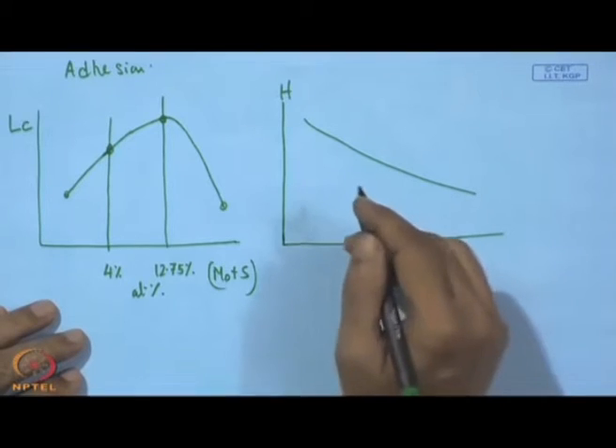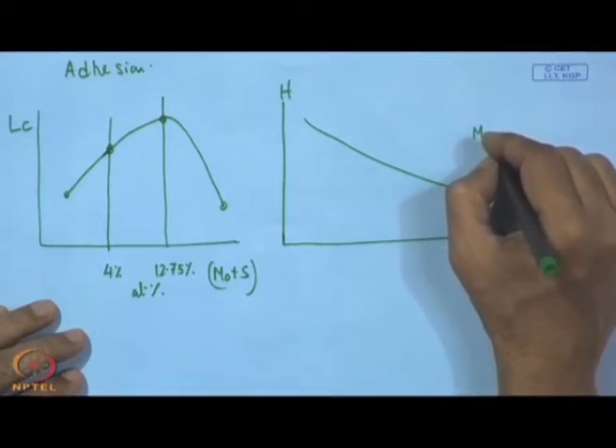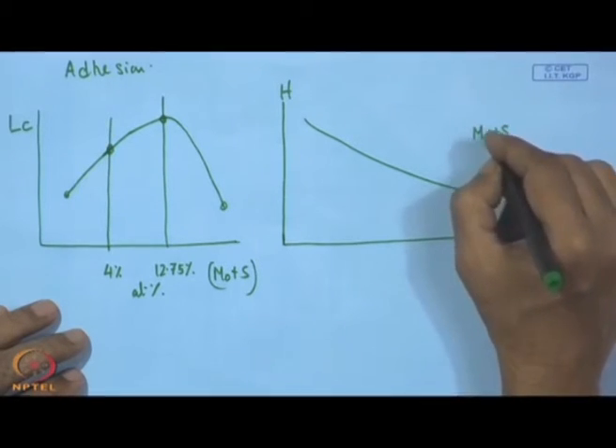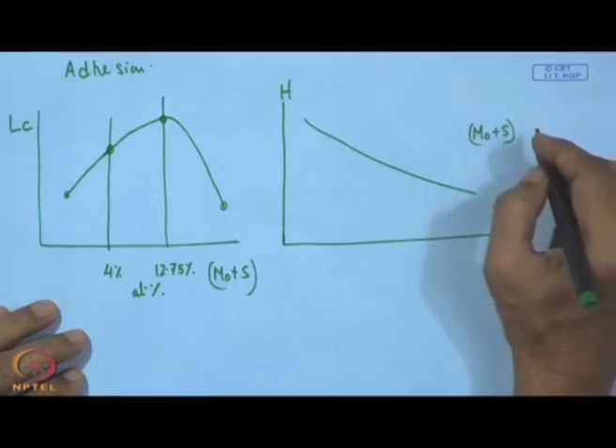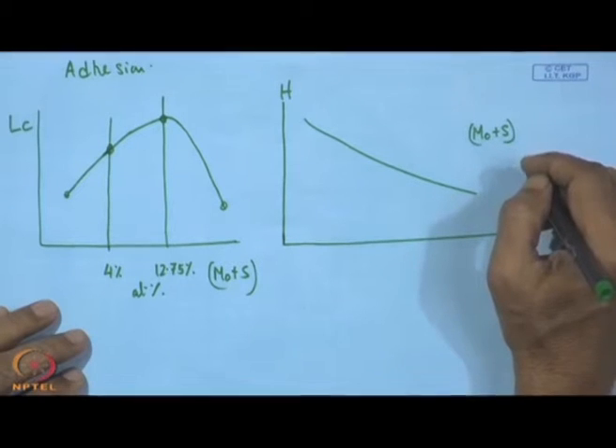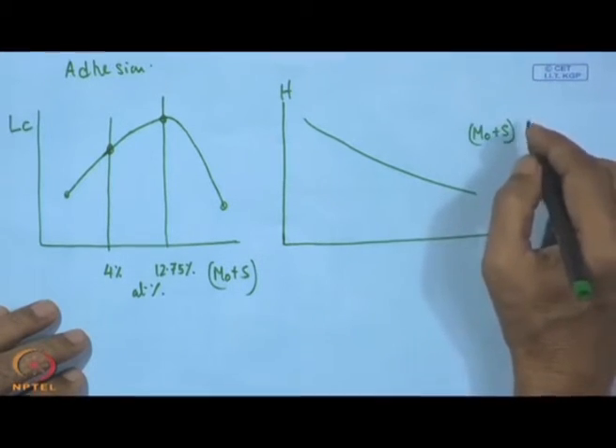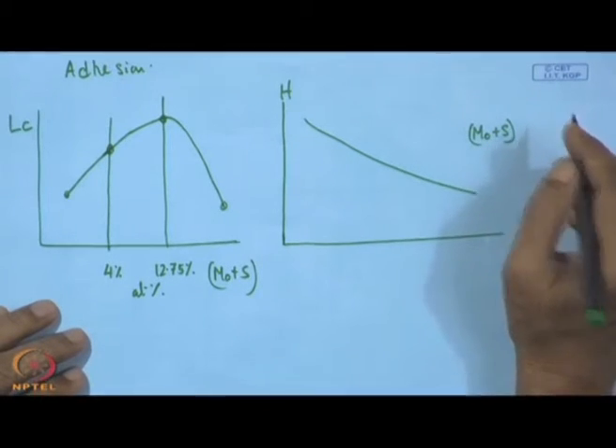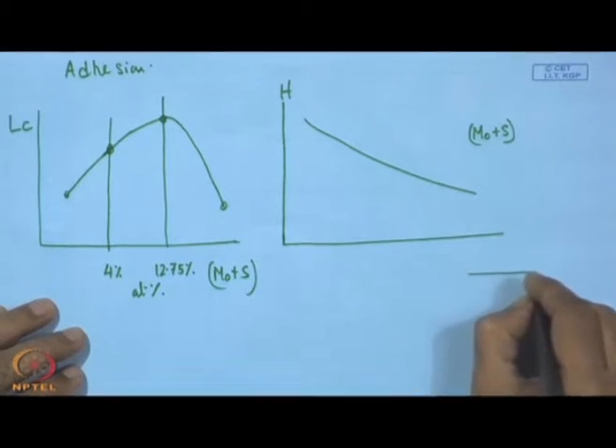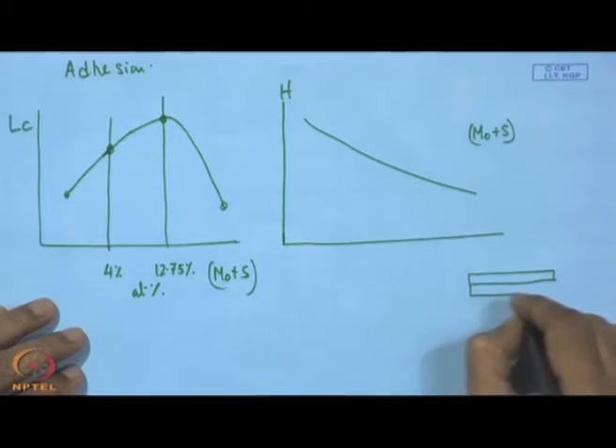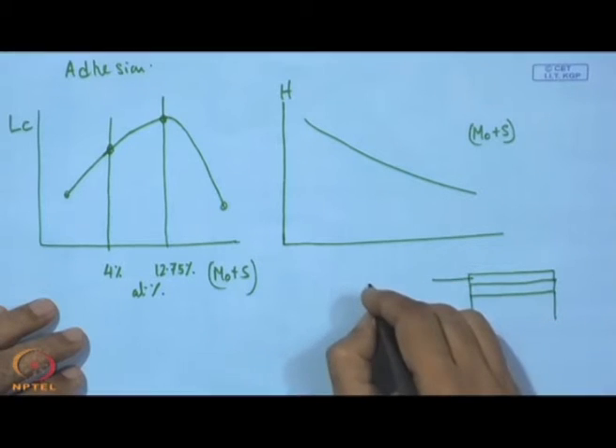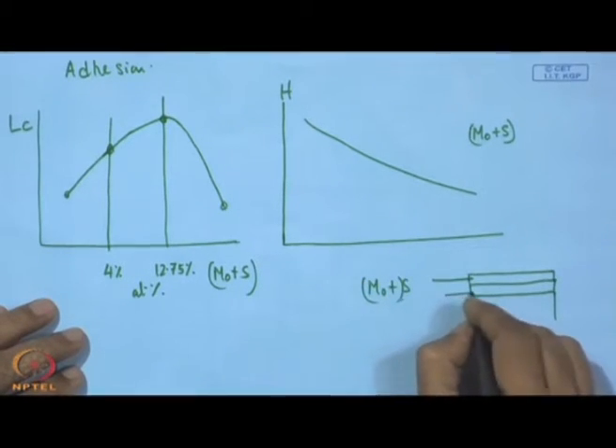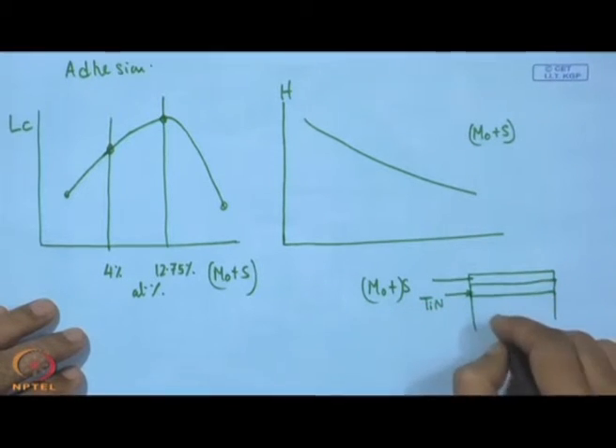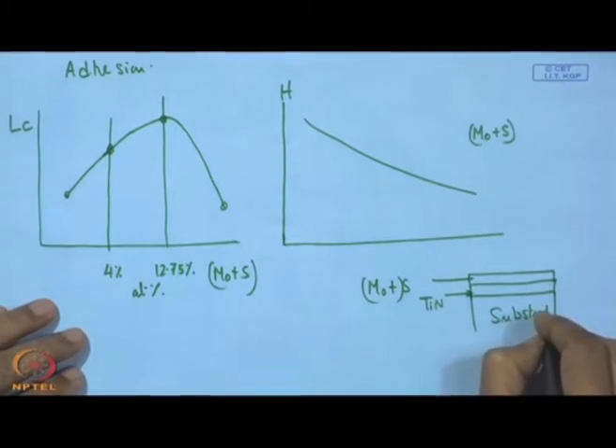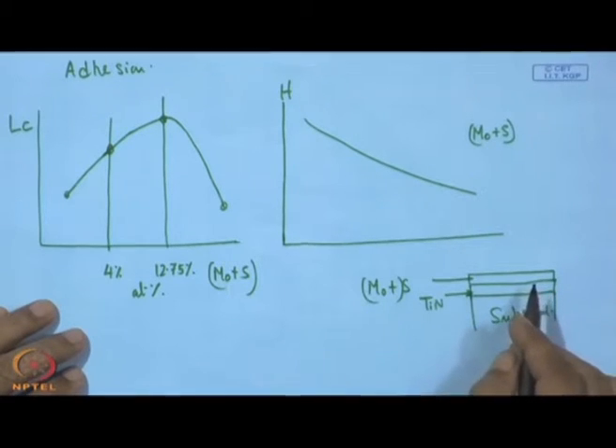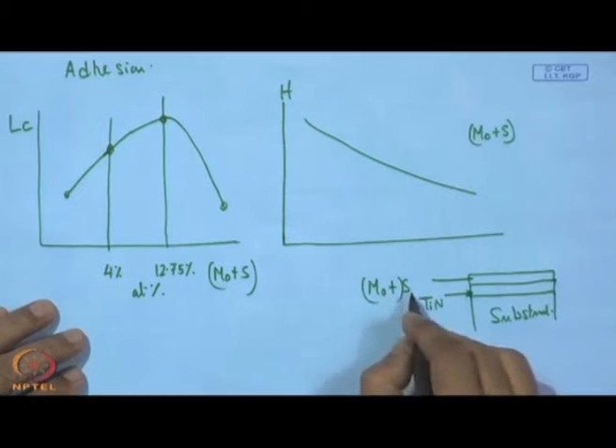The reason is as follows: the higher the percentage of MoS, naturally this is going to be a soft phase, and with this soft phase we have seen that the compound hardness, or say the average hardness of this composite structure, because this is going to be a composite structure. Here what we have, this is going to be the structure, so that this is Mo plus S, and this is titanium nitride. So, when we measure this hardness, the influence of the substrate definitely comes into the picture, and here we have MoS plus also.